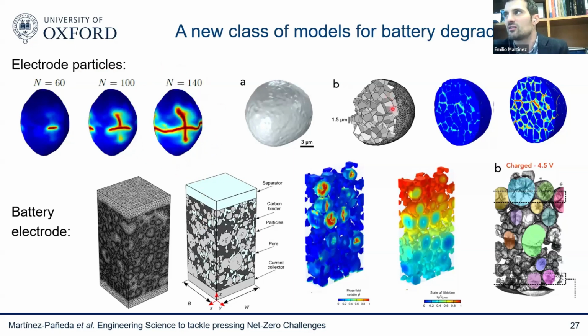We also went down the scales to resolve the microstructure of those particles. So people say Tesla is proposing this million-cycle battery where they're going to use a single crystal. So you remove those grain boundaries that are the weakest link. We can test those ideas in our model. And again, similar to hydrogen, our goal here is to develop virtual platforms that allow you to map safe regimes of operation and also test ideas, test new solutions to battery durability problems, hydrogen transfer problems.